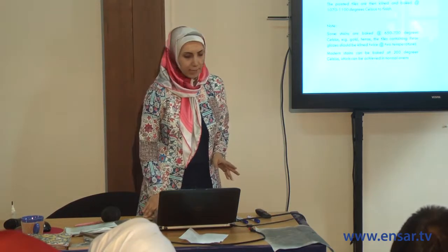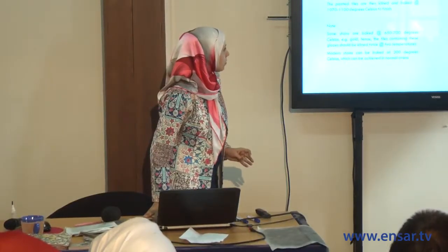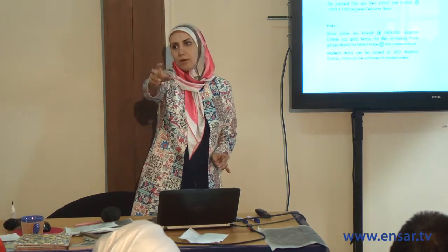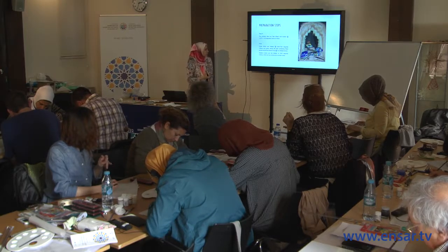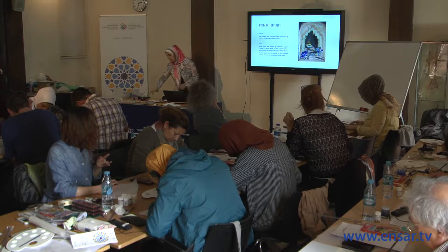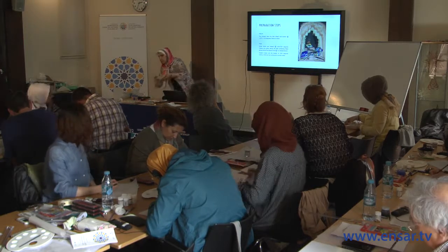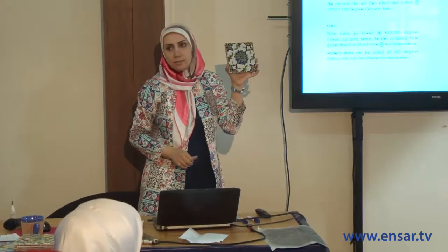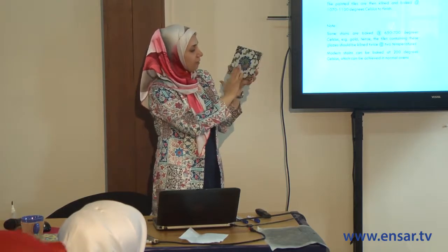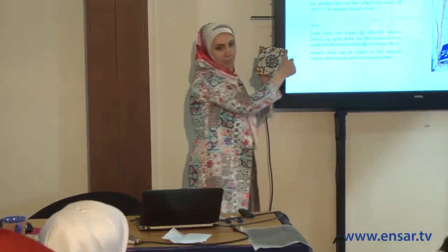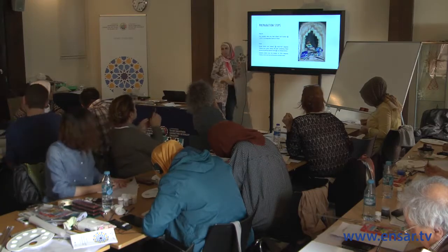The traditional stains and glazes are baked at 1070 to 1100 degrees Celsius. But the inks that we just gave you are modern stains that can be baked in a simple oven at 200 degrees. Sometimes you use, for example, gold color, like this one, in your tiles. The temperature is different from other stains. All the other colors bake at 1100 something, but this one only at 650, 700.